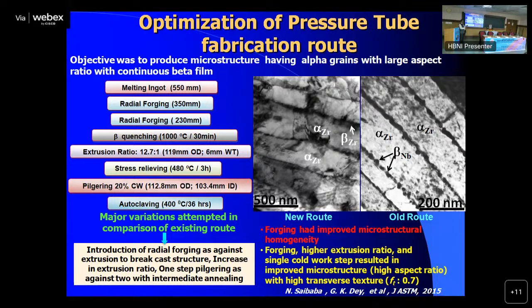For zirconium, texture is very, very important. Okay, so one needs to know how texture will develop, and on that we have done extensive studies and to show how texture will develop in zirconium-based alloys by doing X-ray diffraction, by electron diffraction, as well as neutron diffraction. So all three modes of diffraction have been used for studying texture. So now we have information about phase transformation, about deformation, and about texture development. All three attributes are required for developing a flow sheet for zirconium-based alloys.